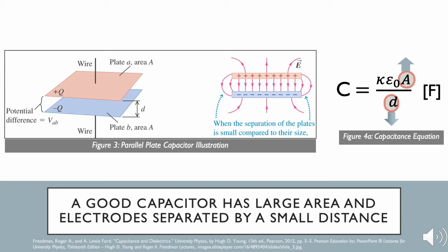Conventional capacitors increase their energy storage by using what is called a high K dielectric material in between the electrodes, which polarizes and thus allows for an increase in energy density. But the fabrication constraints of this dielectric layer lead to an increase in the distance between the electrodes, which then decreases the capacitance. Our research explores the idea of engineering capacitors with enormous interfacial area by combining materials in solution, and then, after casting the solution on a substrate, using the difference in entropy of mixing the two materials as the solution dries to form a large area nanoscale self-assembled composite.